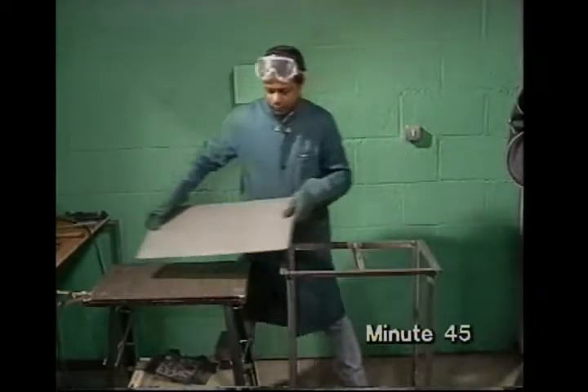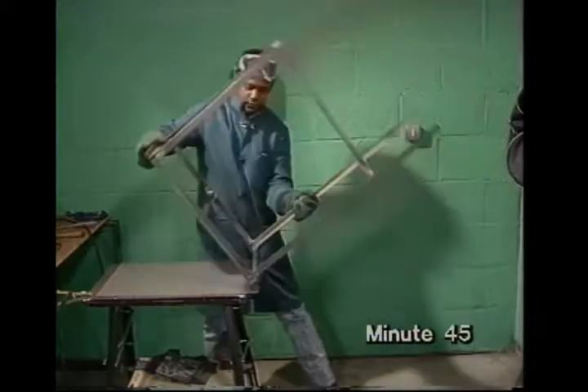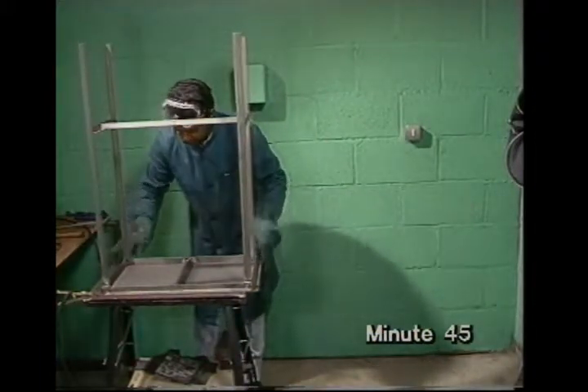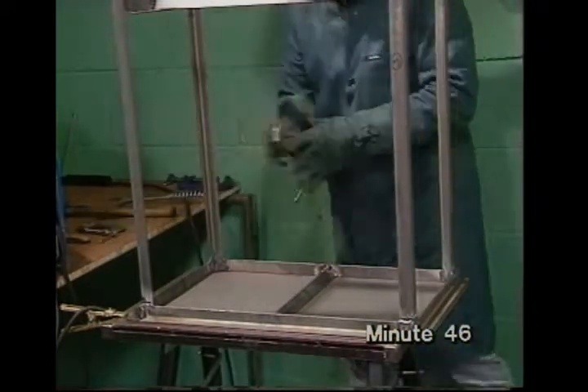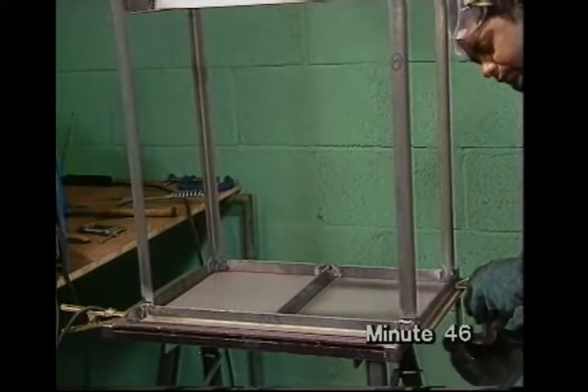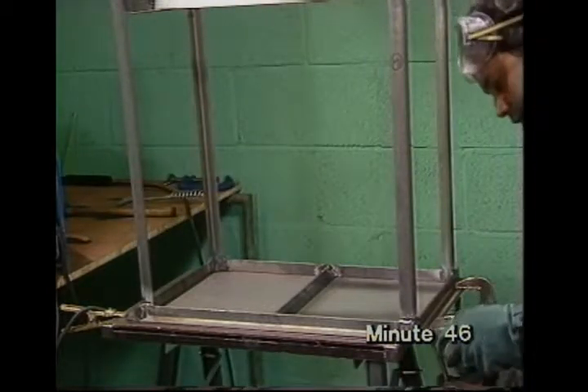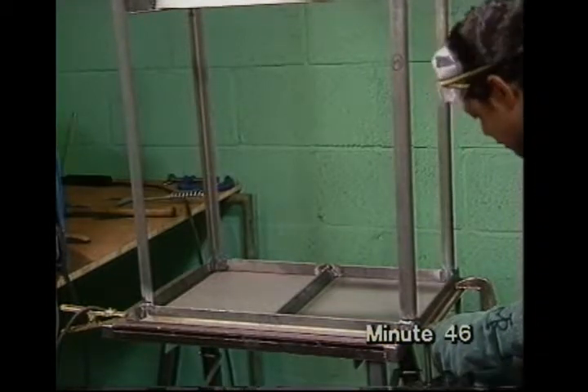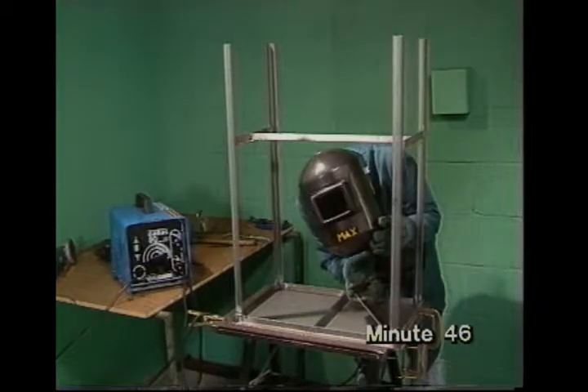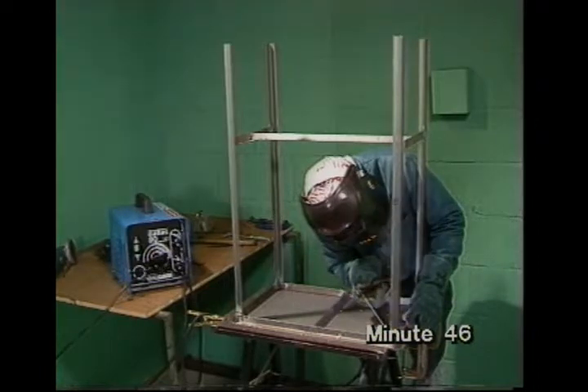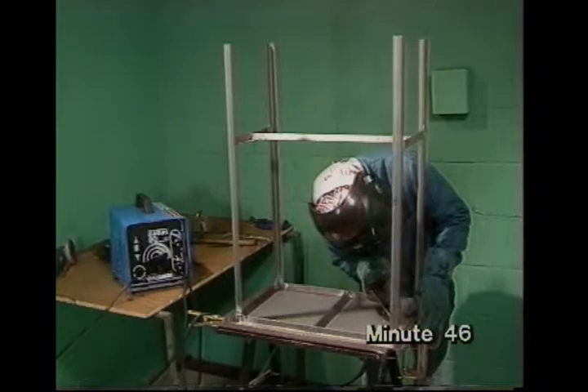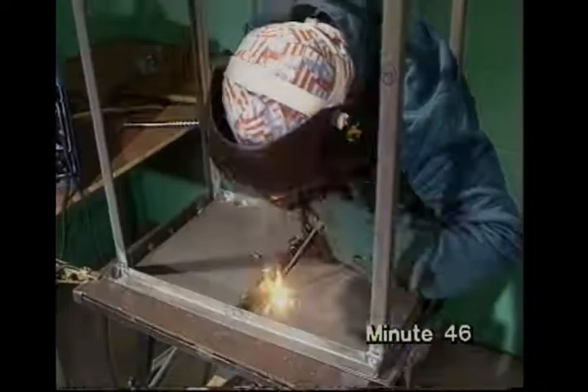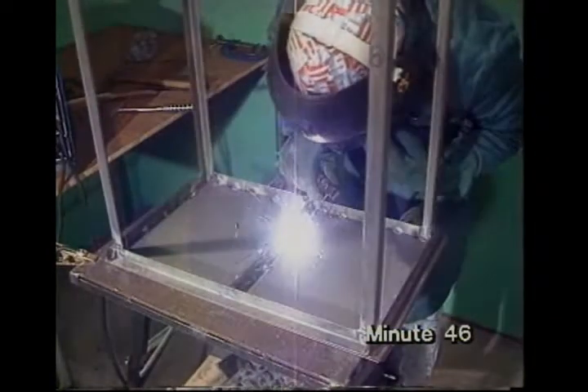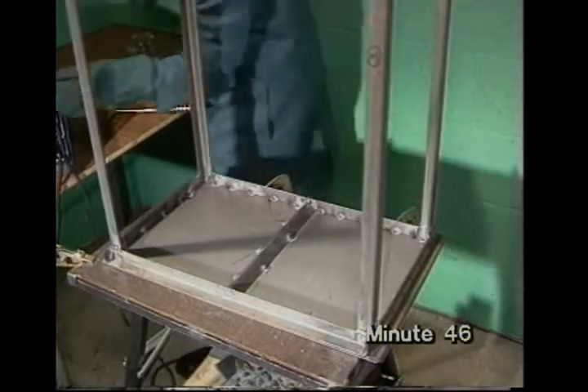With the framework complete and any projecting welds ground flush, the last welding job is to secure the top. Max uses clamps to ensure a good fit, then makes only short welds like tack welds. These are strong enough for the job and take much less time than a continuous weld, but more importantly, a continuous weld would heat the metal much more, and the resulting expansion would distort the thin sheet. Grinding the corners smooth finishes the job.